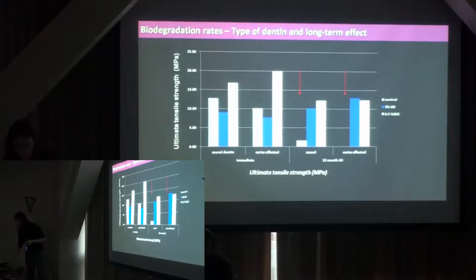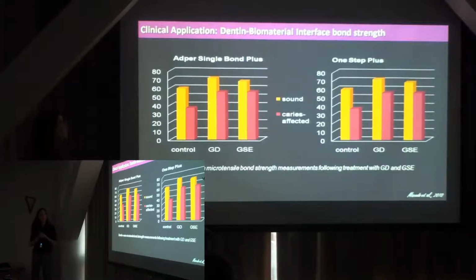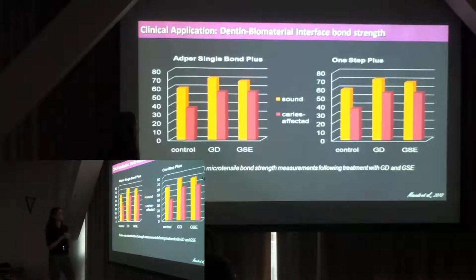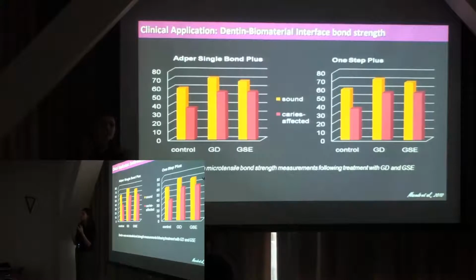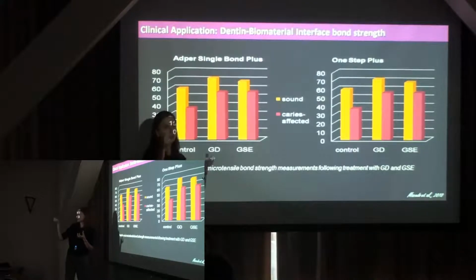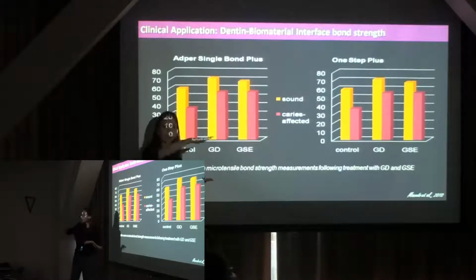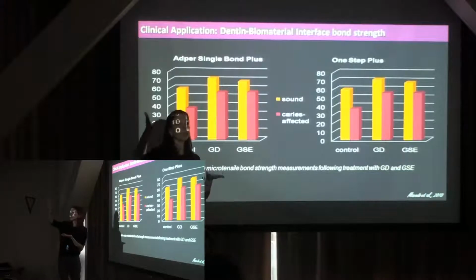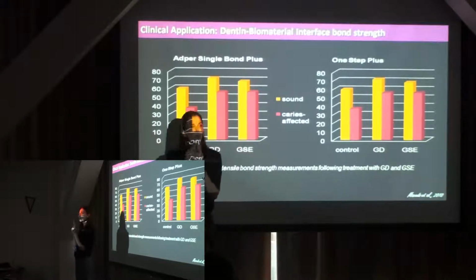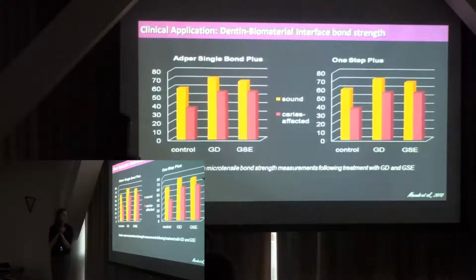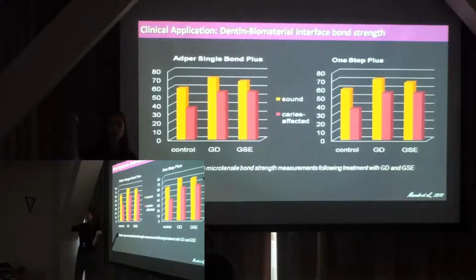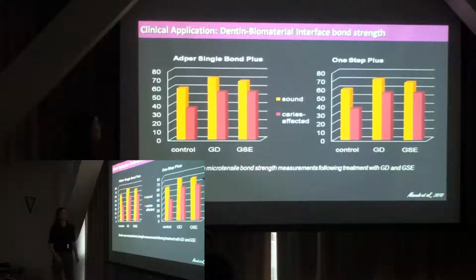I'll skip this. So the clinical application, which is important for us, is that we test the bond between the tooth and the material. So we cut flat the surface of the tooth, and we build it up with this composite. We cut them into small beams about 1 by 1 millimeters thick, and we pull them, and we call this test a microtensile bond strength.